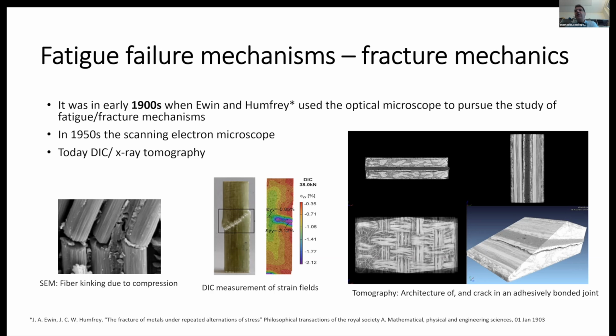And today we have DIC measurements, we have X-ray tomography. X-ray is exactly the same as we do in medicine. When you break a bone, you go to the doctor, they scan your hand or leg or whatever, and they can investigate and check what happens in your body. And the same happens today with X-ray of materials. You see on the right hand here the investigation of, so this is X-ray on an adhesively bonded joint with pultruded composite elements on both sides. And in the middle, this dark one is the adhesive. And there is also a crack, so you can see the crack. And these are outputs of X-ray tomography on this joint.